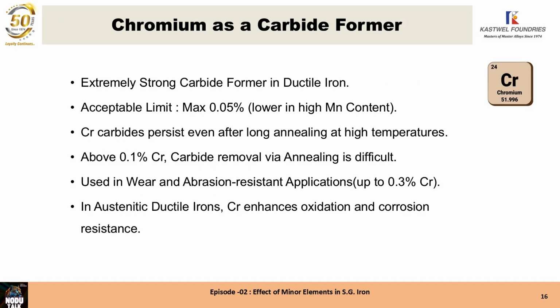Chromium is a very, very strong carbide former. Its limit is 0.05%. Last time when I showed you the figures for different wall thicknesses, the carbon, silicon, manganese, copper, along with the limits for sulfur, phosphorus, chromium, and nickel, I indicated that carbides will form if the chromium content is more than 0.05%.